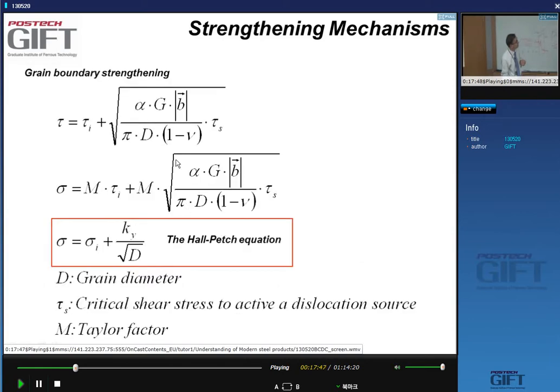So there are different theories for grain boundary strengthening. One of the theories gives the Hall-Petch equation that you all know, that the stress is proportional to 1 over the square root of the grain size. This is the theoretical form of this relation. You see a number of constants like alpha, G, b, pi, d is the grain diameter, and 1 minus the Poisson ratio. So the big parameter here is the critical shear stress to activate a dislocation source.